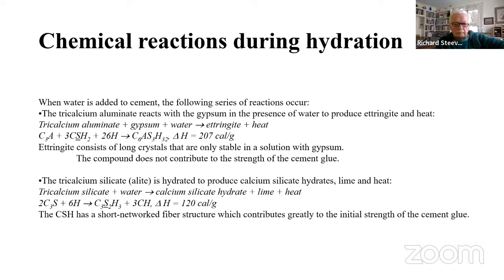And it's this formation of ettringite that slows down the ultimate reactions that result in the hardening of the cement and the reaction with the aggregate that's in the concrete. And the ettringite consists of long crystals that are really only stable in a solution with gypsum. So it turns out that it's not stable without the gypsum, and it ultimately doesn't contribute to any of the strength in the cement glue. But it's important to slow things down initially.